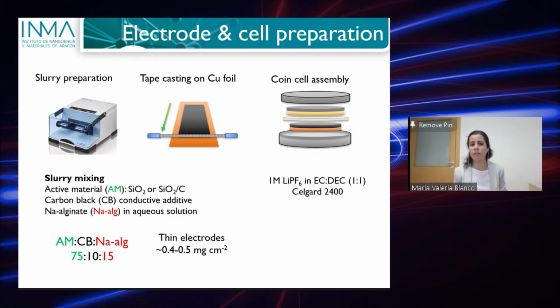So for this we made a slurry, and for the slurry we mixed 75% of this active material, that is the silica composite, and then we added some carbon black that serves as a conductive additive and helps the conductance of the ions within the electrode, and then some binder, that was a sodium alginate binder that would help to connect all the components of the electrode.